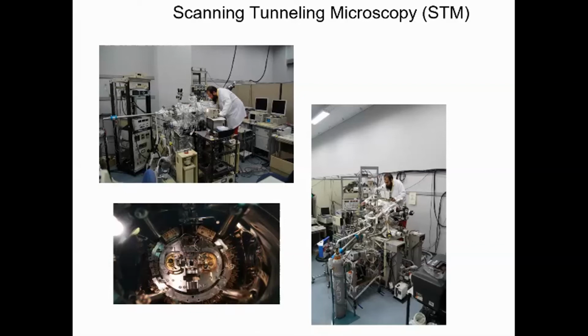The difference between the STM and the AFM is that AFM looks at the lateral resolution itself and can work in ambient conditions. But the STM works in ultra high vacuum and can also vary the temperature. But we are looking at the electron cloud itself, because it's looking at the electron density. It's no longer looking at the lateral forces like the AFM.